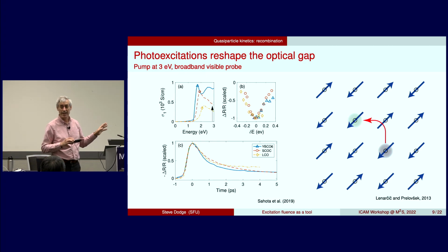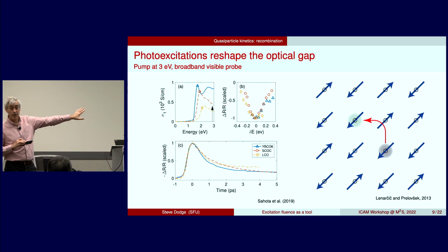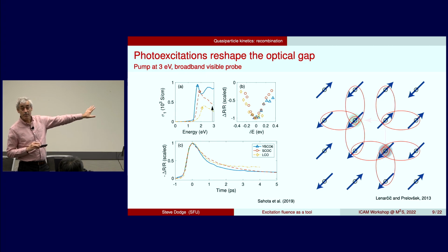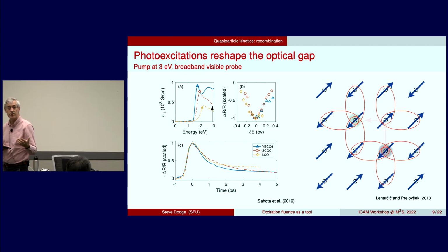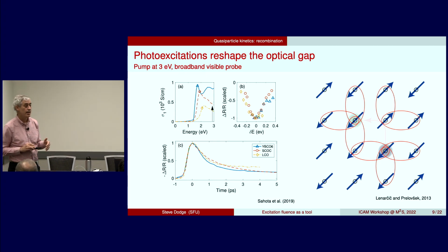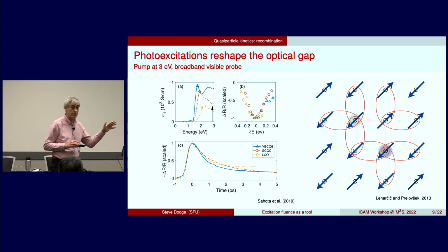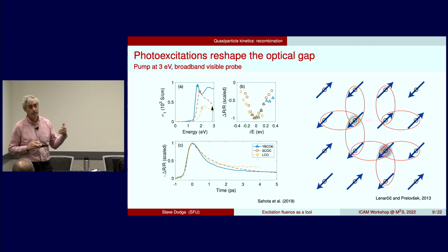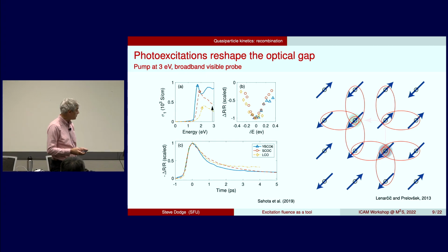They did it quantum mechanically with all the details. What you'll notice when I did that hopping is that I now broke 8 bonds. And if you assign an eighth of an eV to each of those bonds, you've got an eV of energy that you've just given up in that process. And so you have a way to give off a lot of energy through magnon emission through just one single process. It's much easier to imagine that you could give off that energy on a short time scale.